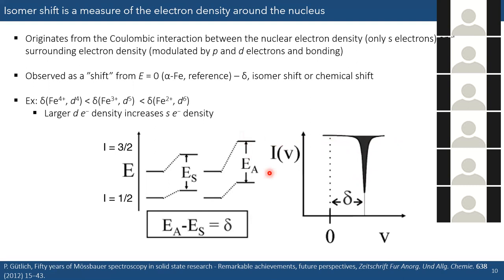But very likely, the specific gamma ray energy required for this absorption event is not going to be the same as it was in your source material. Therefore it's modified slightly in energy. It's going to appear at, say, higher energies, shifted away from zero, which is the set point for your reference, by this little delta, which we call our isomer shift or chemical shift. I should note that for iron Mössbauer, most commonly alpha iron is used as a reference. So you take the spectrum that you get, put in this reference of alpha iron, and set that to zero.